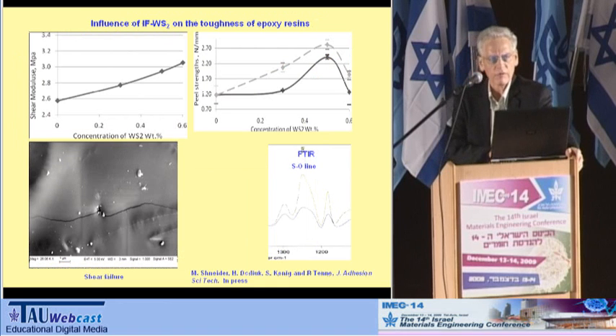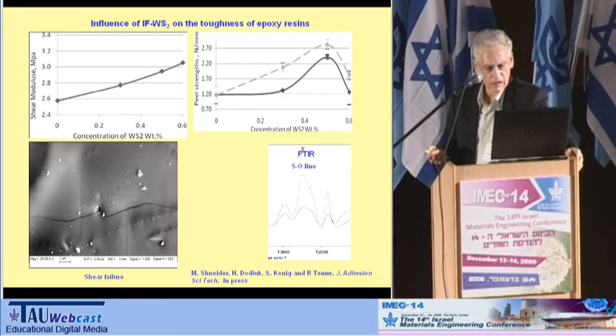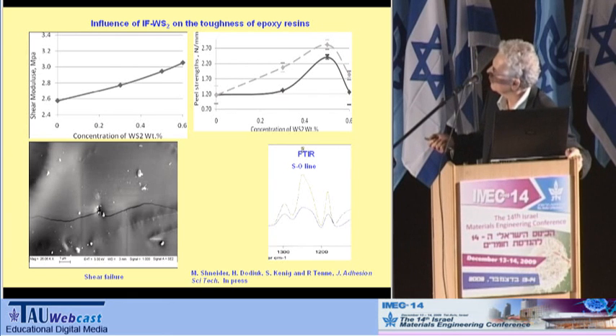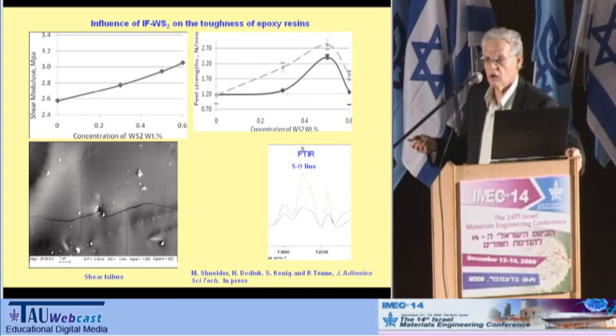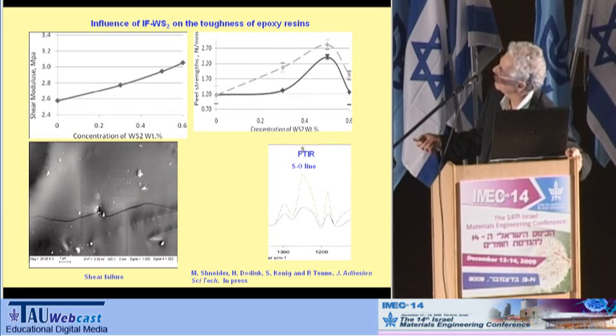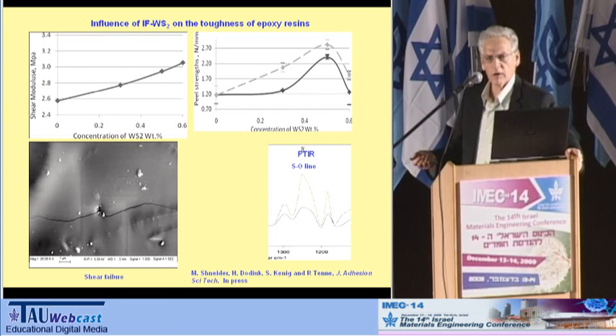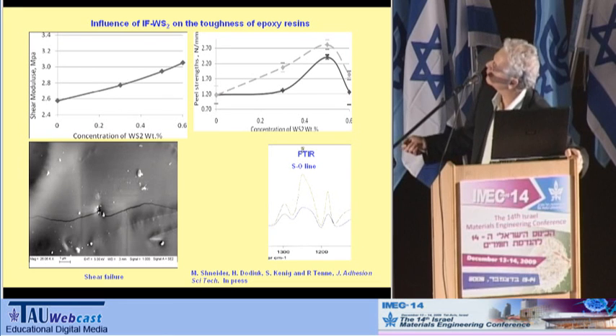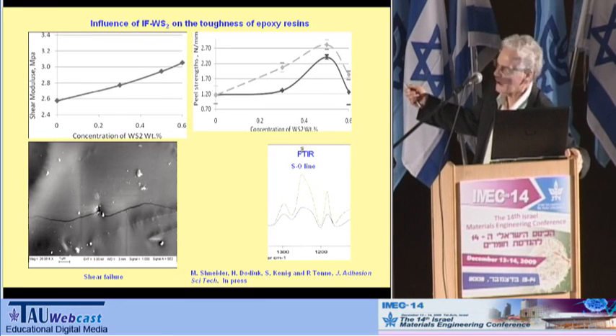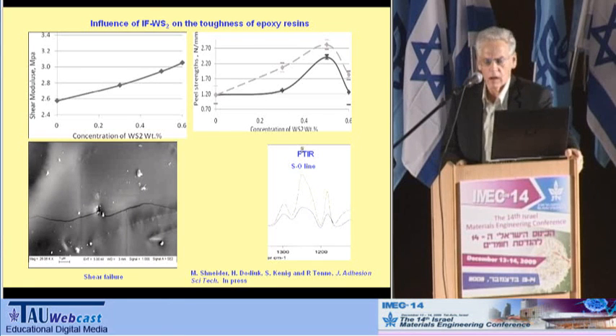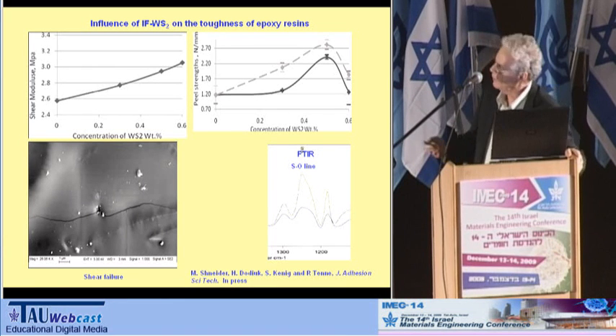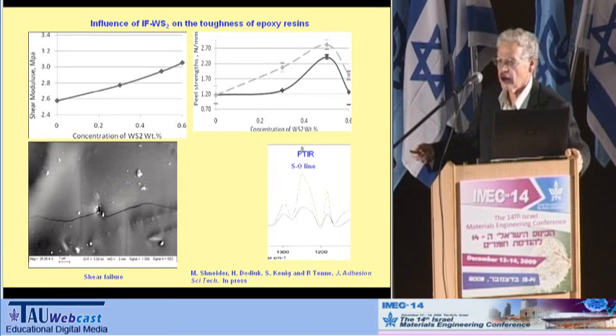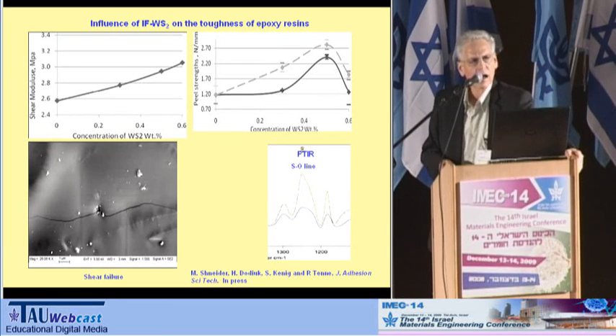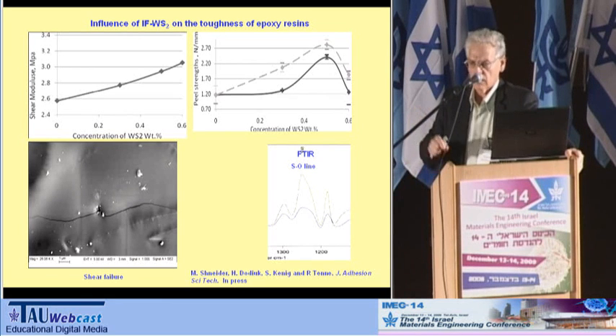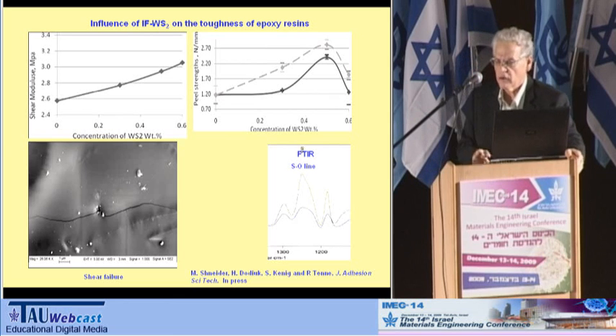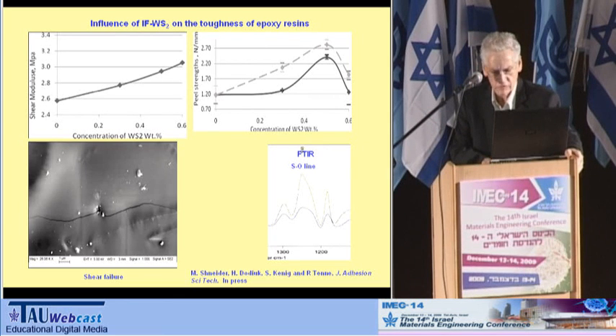And this is a recent work which is now in press, joint work with Professor H. Dodiuk and S. Kenig at the Shenkar College. The student Mark Schneider did a very beautiful work where he added these nanoparticles to thermosetting polymers, to epoxies, and showed a tremendous increase in both modulus and the peeling strengths of the polymers. These are aircraft quality or aerospace quality polymers. And he furthermore showed, using FTIR, that a new S-O-C bond is formed between the polymer epoxy group and the outermost sulfur layer of these nanoparticles.